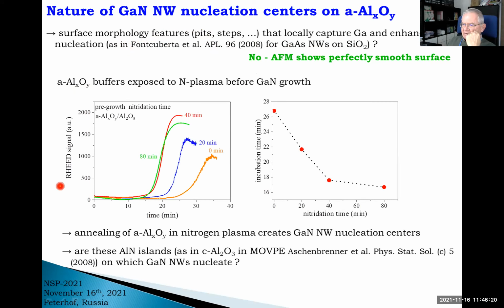What we see instead is that the incubation time strongly depends on the time of exposure of the aluminum oxide buffer to nitrogen plasma before growth of nanowires. So this is the example. This is again the RHEED signal profile. If we open the gallium and nitrogen cells at the same moment, this is the incubation time, which is something like 27 minutes. In this case, we exposed this buffer to nitrogen plasma for 20 minutes at the growth temperature, and only then was gallium opened. And you see that the incubation times become shorter and shorter.